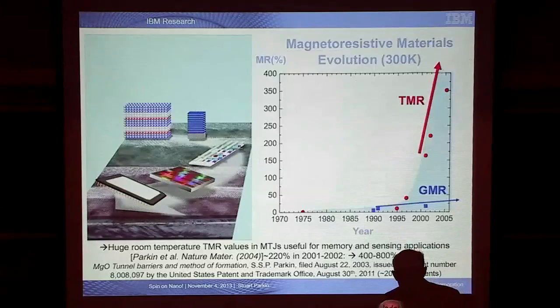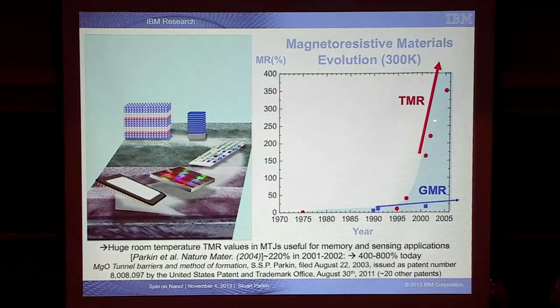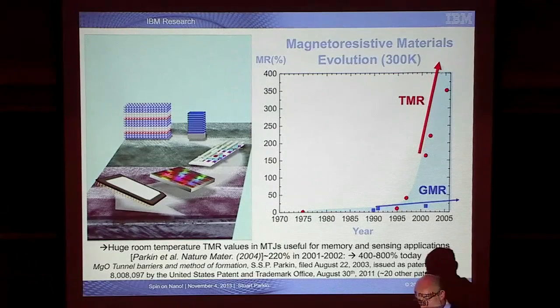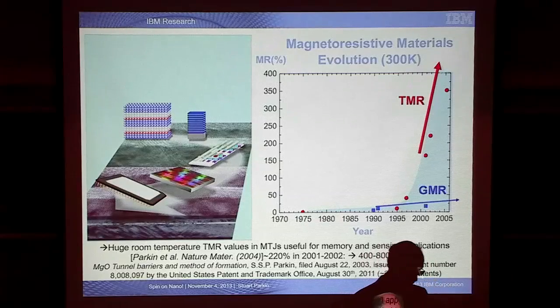It means that if we look at the magnitude of what I've called this tunneling magnetoresistance, the percentage change in resistance of this tunneling junction when you change the magnetic layers from being parallel to antiparallel, in 1995 was the first observation of any tunneling magnetoresistance at room temperature. And 2001 was when we found this magnesium oxide material. You can see today, we can see changes in resistance of nearly 800% at room temperature. So there's been a remarkable discovery of materials and this physical phenomenon in just the last 15 years or so.